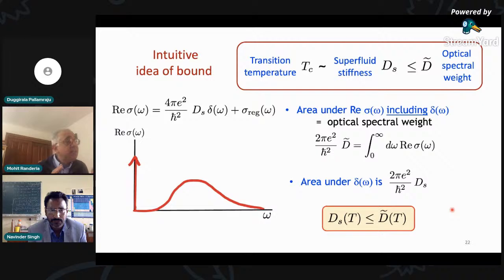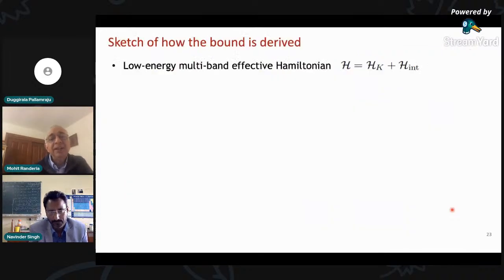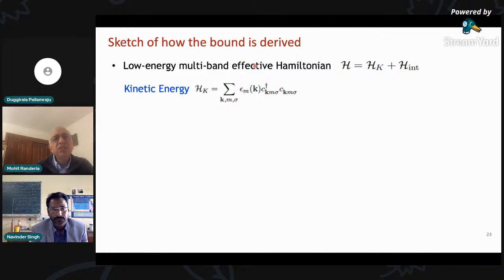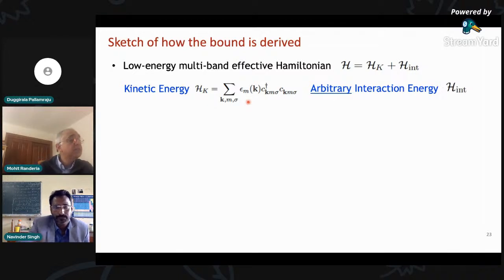Now, this is a very hand-wavy argument. And since this is a very serious bound, let me take 2 seconds to sketch how this hand-wavy argument, which is physically very compelling, is actually derived rigorously. So I know this is not a seminar, it's a colloquium, but for one slide, since it's a real bound, please humor me and I will tell you. So we start with a general multi-band effective Hamiltonian, in which there is a kinetic energy with arbitrary band structure for multiple bands that are crossing the chemical potential, and we allow for arbitrary interaction energies.